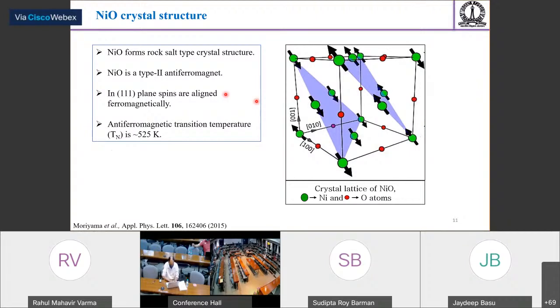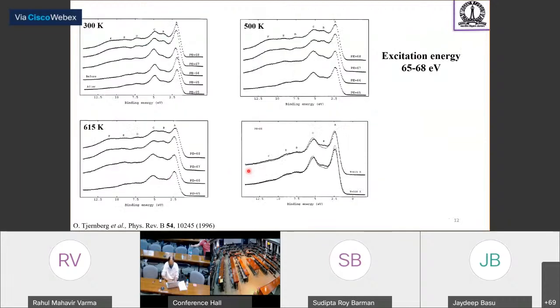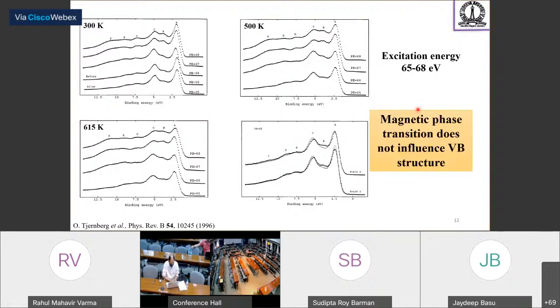Nickel oxide forms a rock salt type crystal structure where intralayer spins are aligned ferromagnetically in the 111 plane, and interlayer spins are aligned antiferromagnetically. It has an antiferromagnetic transition temperature of 525 Kelvin. So one can ask a question here: does this magnetic ordering influence the electronic structure or not? In 1996, Tjernberg et al. performed a photoemission experiment at three different temperatures, 300, 500, and 615 Kelvin. And after a detailed analysis, they concluded that the magnetic phase transition does not influence the valence band spectrum.